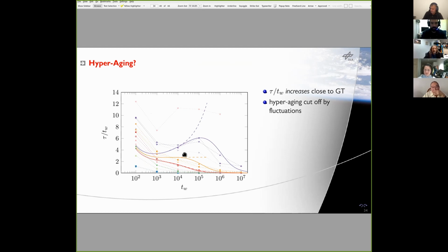And again, the colorful symbols are all computer simulation results from papers co-authored with Magdaleno, I think, from various people in the audience here. And the lines are 3 examples of the combination of the non-equilibrium Langevin equation theory with the scaling laws of stochastic beta relaxation theory for quenches to a state in the liquid in red, to a state in the ideal glass in purple, and to a state at the critical point in yellow, where the ideal MCT prediction would be that the structural relaxation time grows linearly with the waiting time. So this ratio should approach a constant.